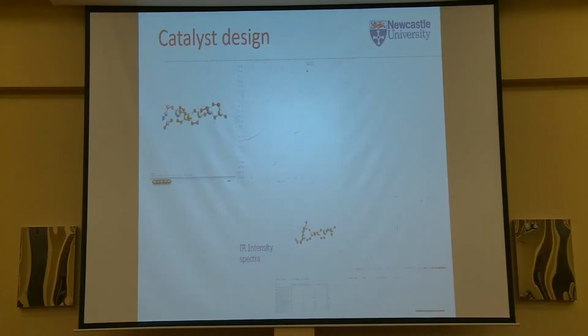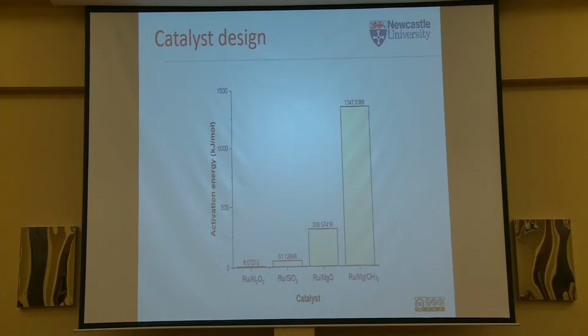And so from this type of analysis, we've built some stuff like this, and you can see some of the transition state estimates for different materials that we have considered. So at the end of the day, you have a result like this, and this particular one is for ruthenium-based catalyst. So for ruthenium-based catalyst, considering different supports, we can see the energy barriers that are associated with the various options. So from what I was explaining, by looking at this, you see that the ruthenium catalyst on alumina support for this specific comparison is likely going to achieve our target of operating at a lower temperature than a ruthenium-based catalyst that is using magnesium hydroxide support, for instance. Okay, so that's the point of the computational study that we are doing.